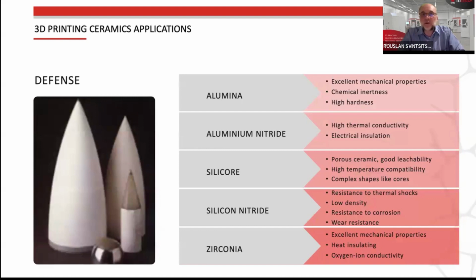Of course, other materials are also used when we speak of space. We can speak of defense as well. Other materials can also be non-oxides we have in our portfolio, like aluminum nitride or silicon nitride, and some silica-based materials for radomes, for example, for those who are familiar with this application. So Silicore is a porous material, it's not dense. It's about 35 to 40% porosity, but it's a high temperature resistant material, and additive manufacturing allows us to make complex shapes with this material. Zirconia, of course, as I said, we have 2 types: 3% yttria zirconia and 8% yttria zirconia, which are used both in defense and aerospace applications.